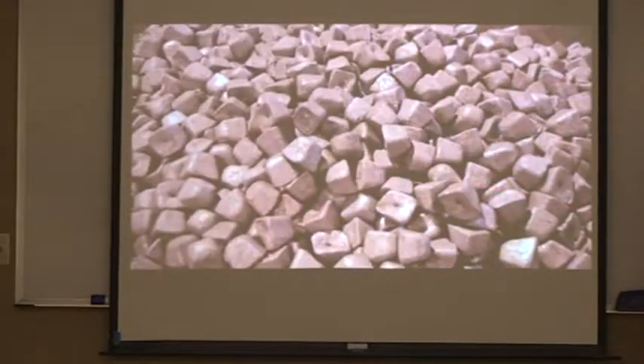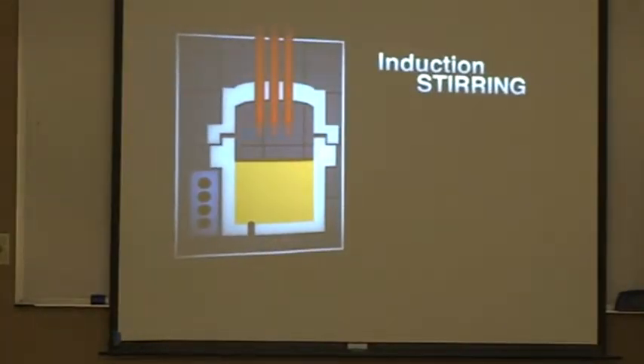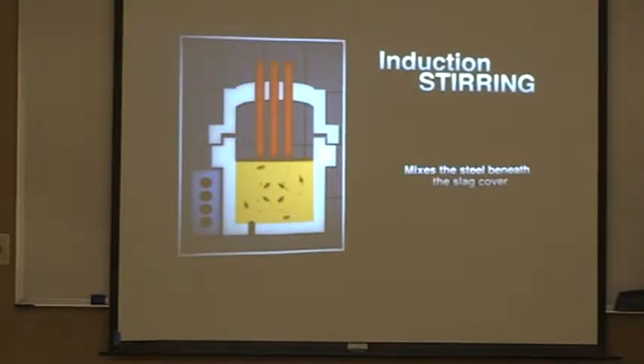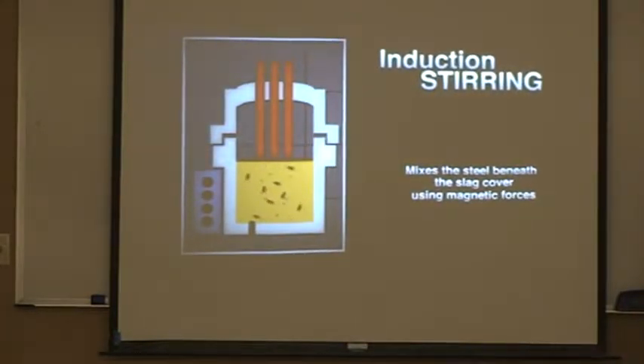Here at the ladle refining station, the alloy calculation program consistently brings the chemistry to the aims supplied by our customers. The alloy additions are automatically weighed and transferred from bins into a hopper and then charged into the ladle. To ensure chemical and temperature uniformity, the process requires induction stirring. Induction stirring mixes the steel beneath the slag cover using magnetic forces. In addition to helping to create a uniform bath, the induction stirring also aids in the removal of non-metallic inclusions by creating opportunities for them to be absorbed into the reducing slag.